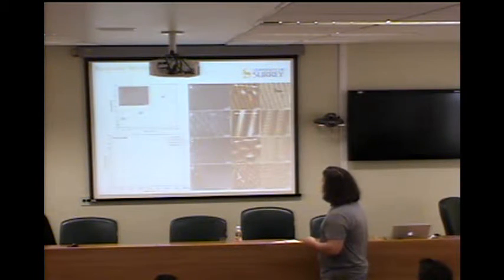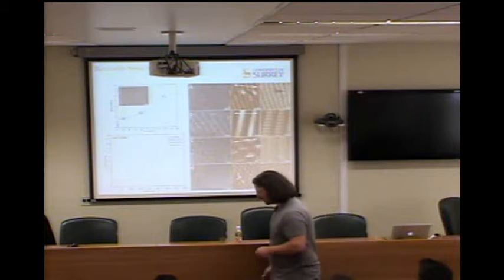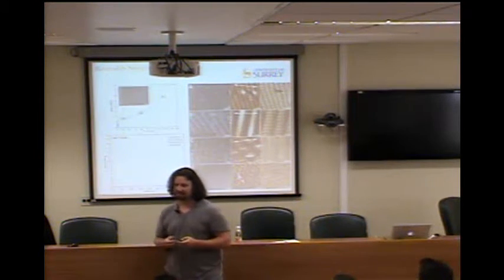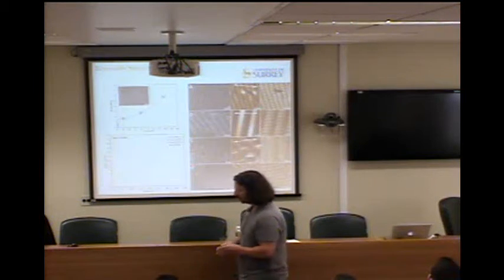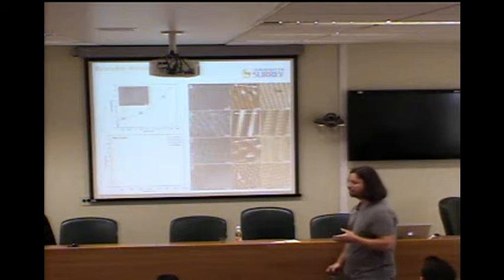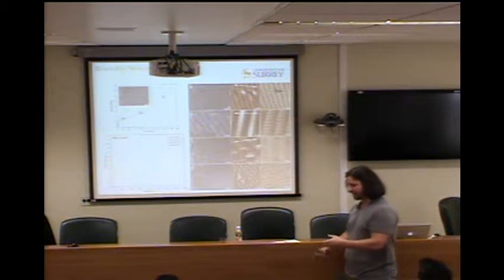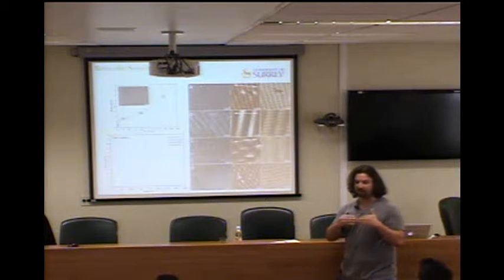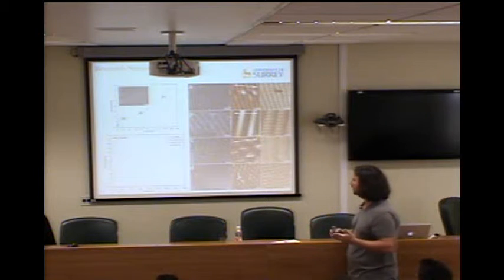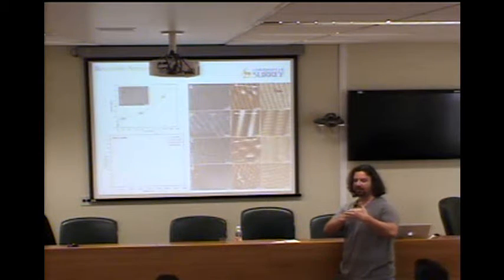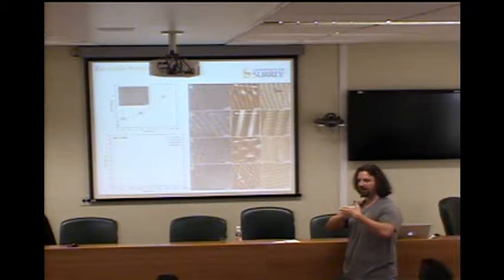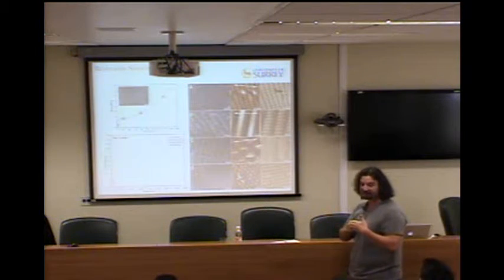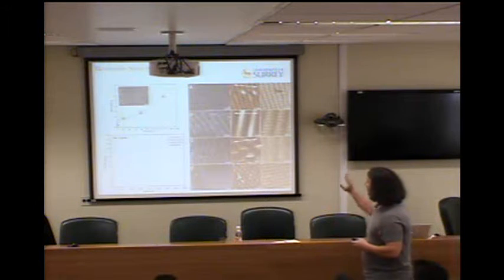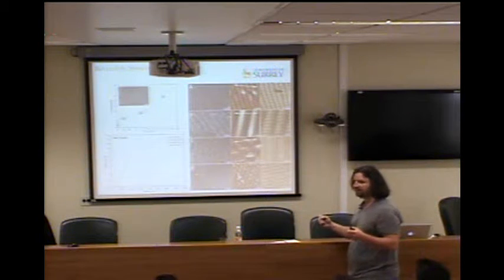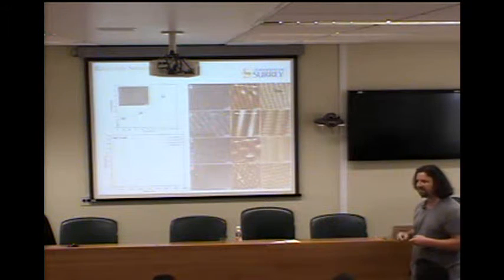What's very interesting here is that these particular systems allow us to make stretchable conductors. So why is that interesting? Well, if you take a normal composite system where you add an electrical filler and you pull on it, the nanoparticles will move and they'll break their connection to each other, and you lose your electrical conductivity. In this particular case, the carbon nanotubes are in these interstitial sites, but they're just sliding along each other. So they maintain electrical contact throughout. And so you can stretch this to 300% of its original length, and the conductivity only changes by 1%.